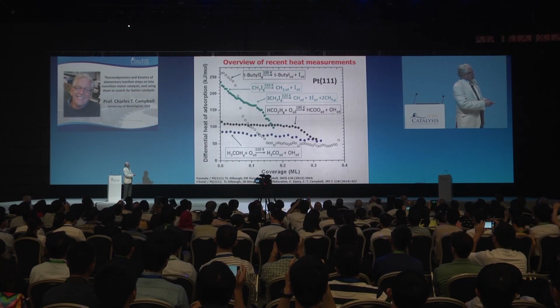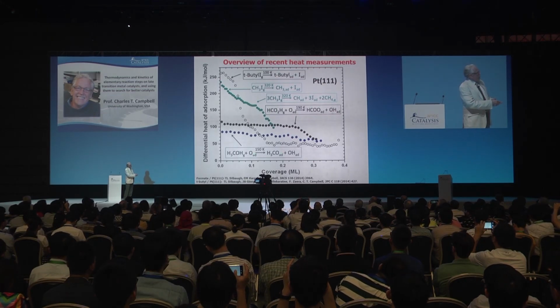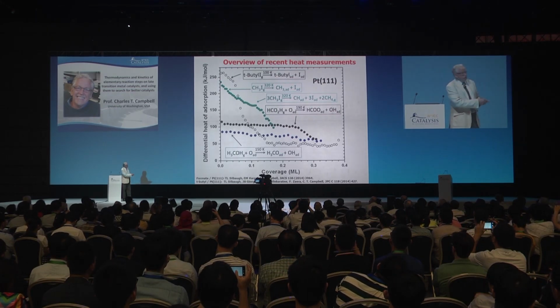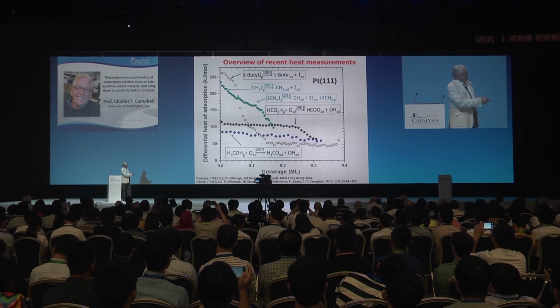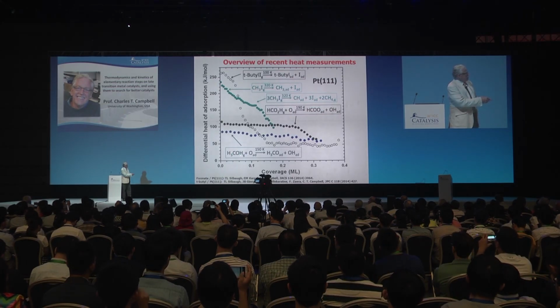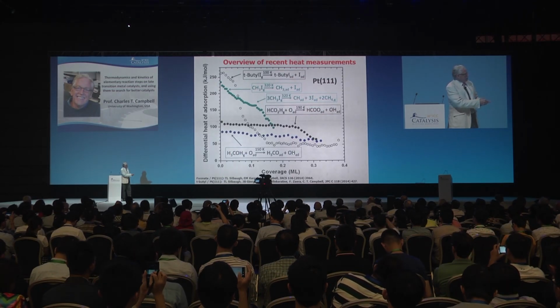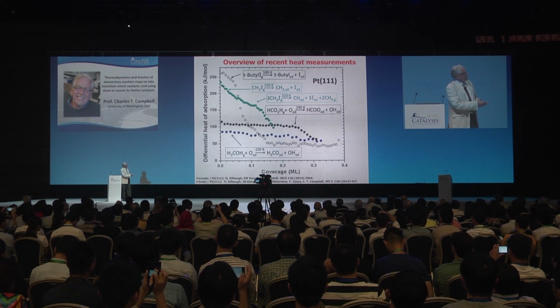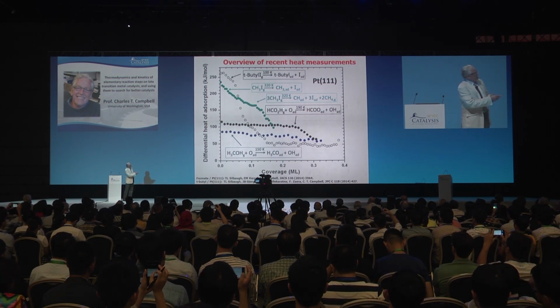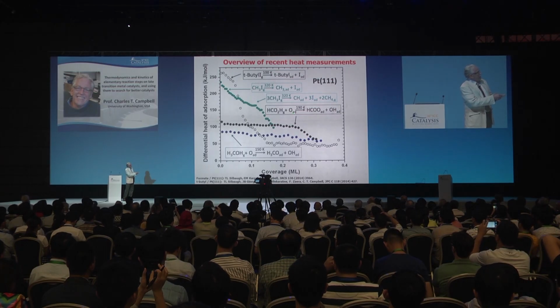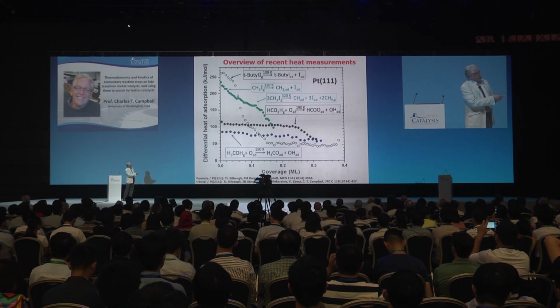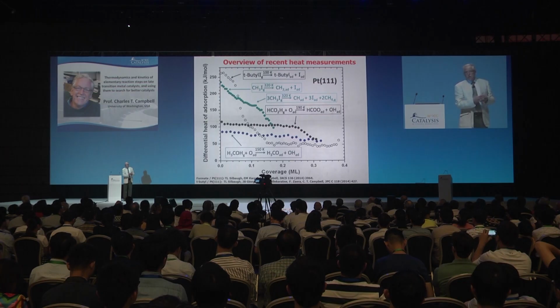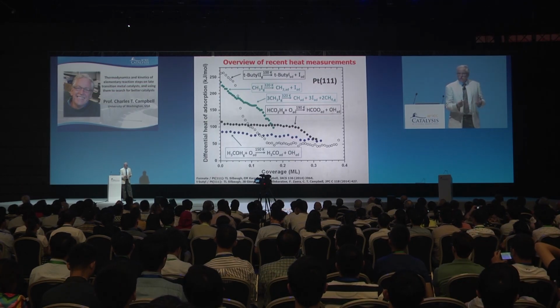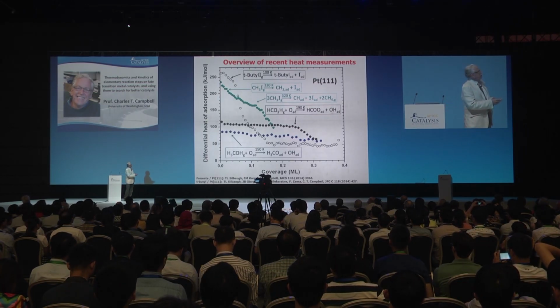And so here's a collection of such measurements. We can get the heat of formation of methoxy groups from the reaction analogous to the water dissociation, where we have oxygen. You lose the acid hydrogen, if you like, on the methanol to make methoxy and OH. If you similarly adsorb formic acid, you lose the acid hydrogen to make formate and OH. And depending on the temperature where you do that experiment, you can make either monodentate or bidentate formate.